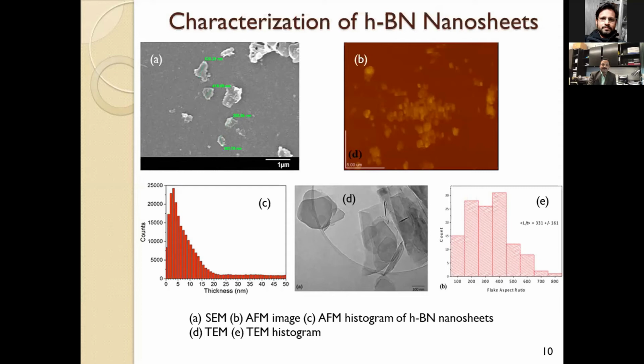In the AFM, these results are further consolidated, and in the TEM, we can see that there are about 9 to 10 sheets in every flake, which means that the thickness of every sheet comes out to be roughly 3 nanometers, and the aspect ratio, which is the ratio of length and thickness, is about 331.